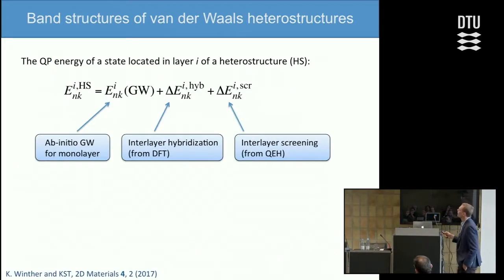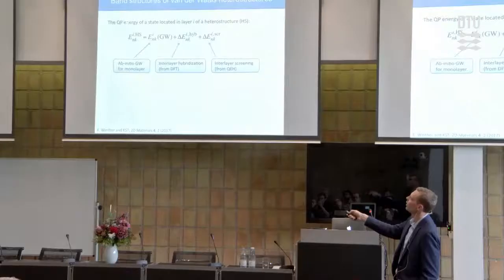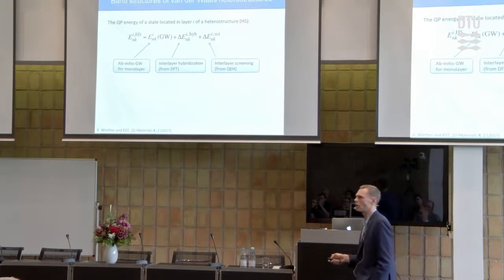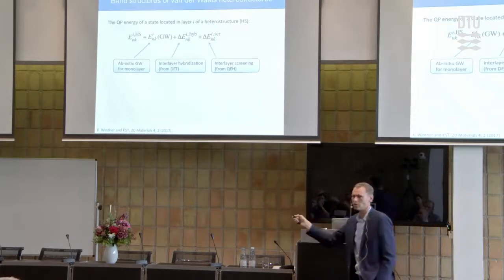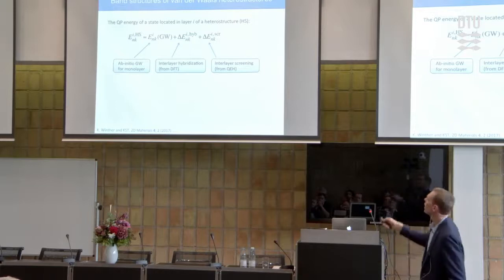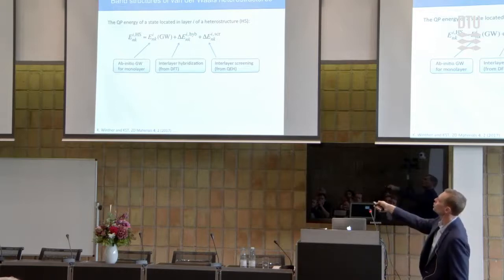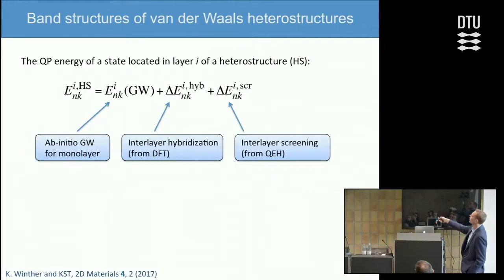To solve that problem, we've developed another method where we compute the energy of an electronic state of a two-dimensional layer embedded in a heterostructure—say layer i, state Nk. We write that as the energy of the electron in an isolated two-dimensional layer, which we can easily calculate, and then add corrections due to hybridization between the layers. That's easy, we can do that with DFT.